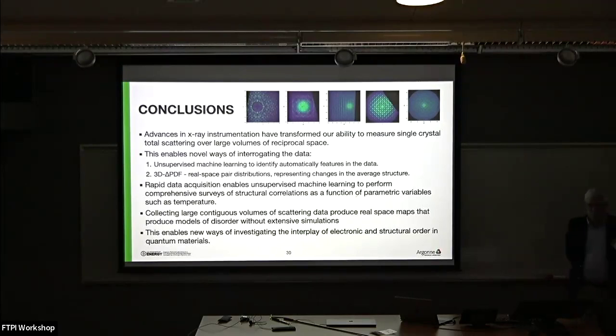Just a small comment regarding vanadium dioxide. You mentioned that you want to see first principle calculations. A word of caution: it is very well known and well established that vanadium dioxide dimers form through a Peierls distortion. What happens is that they form a true singlet, which is not a singlet orbital state and cannot be described by density functional theory by definition. We worked a lot on describing radiation damage in vanadium dioxide, and it turned out that if you try to put straight DFT or DFT plus U, whatever, it actually freezes in the anti-ferromagnetic state, which is not right.